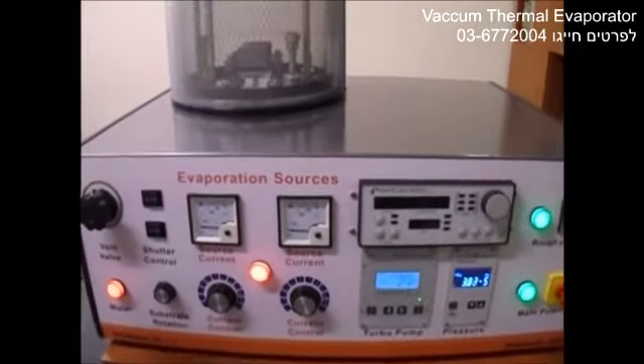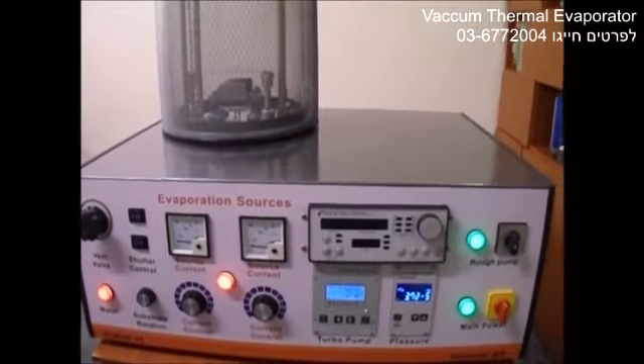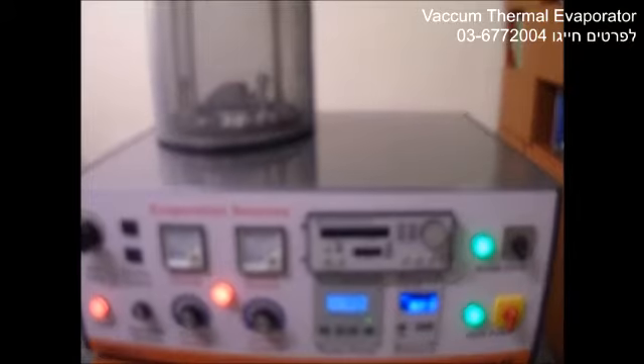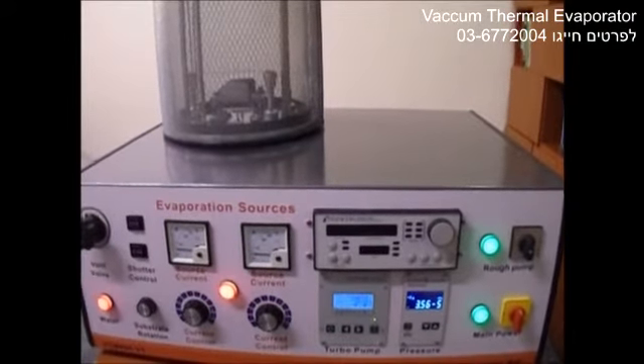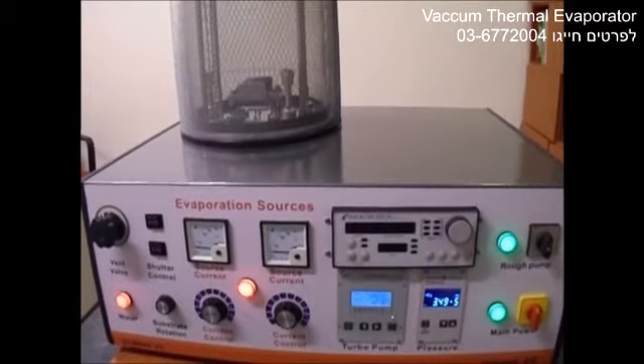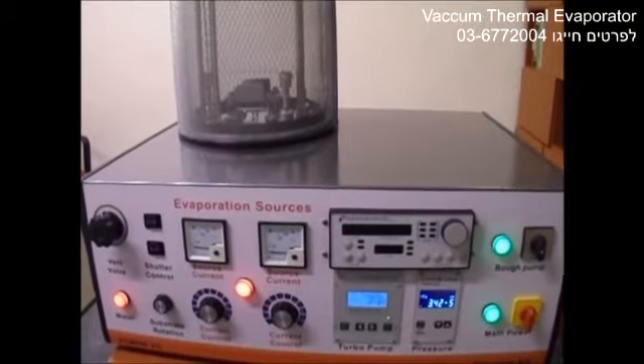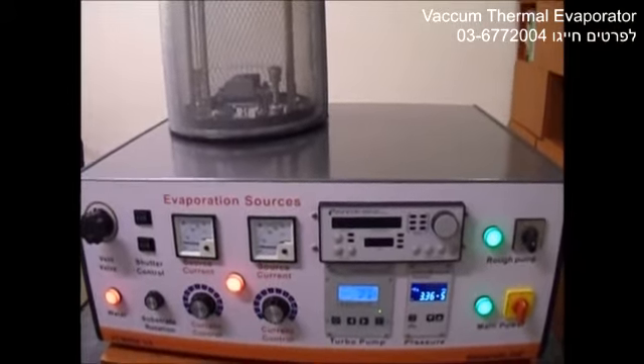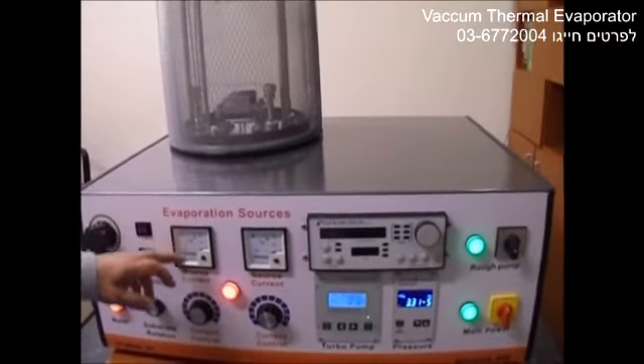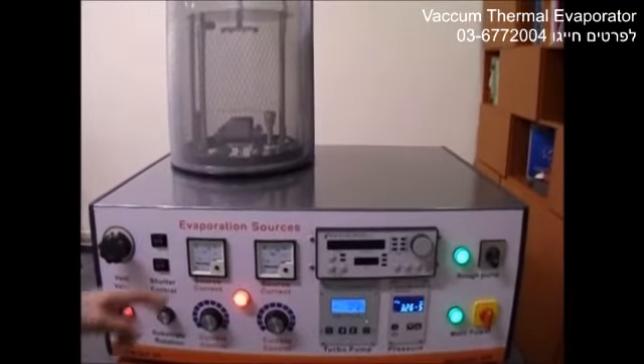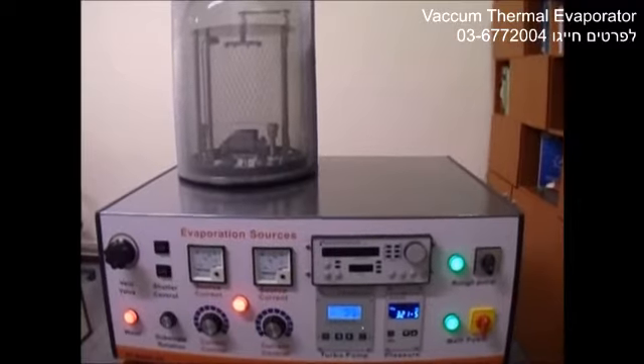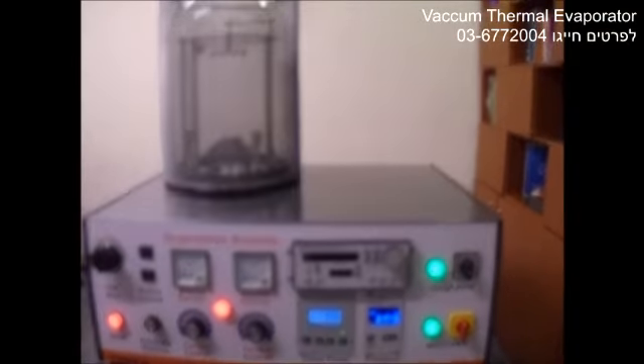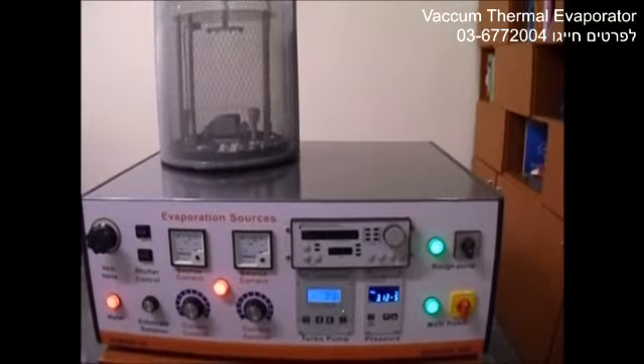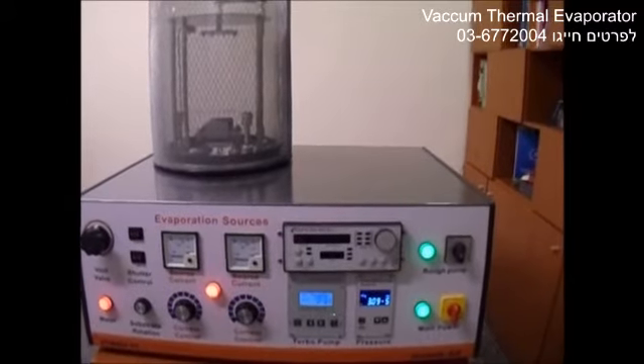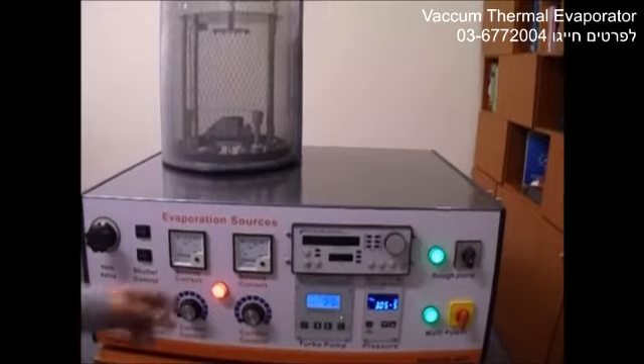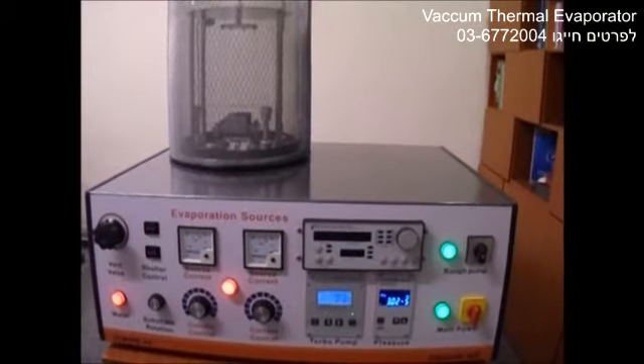Finishing the deposition, we can wait for the turbo pump to stop. We use two different sources, independently driven, to allow us to evaporate two different types of materials without breaking the vacuum. For example, it's very easy for us to have chromium in thermal source number 1 and gold in thermal source number 2. We use chromium to produce a very thin film that has very good adhesion on the substrate. Then we use gold to produce the desired thin film.